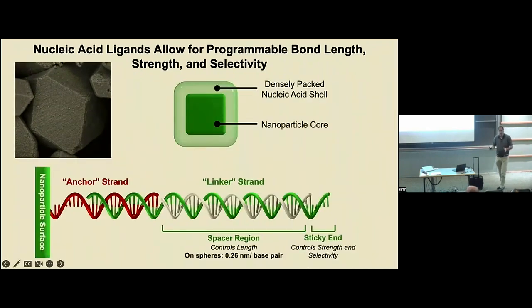Well, we were getting stuck in kinetic traps, right? We were using longer oligonucleotide lengths, and the bonds were actually too strong. And so we were stopping en route to crystallization. And so the trick was to build architectures that maintain directionality. Just tagging things with DNA doesn't work here. Density is really important. Having oligonucleotides all the way around the structure, forcing the oligonucleotides to stand upright and adopt the directionality imposed by the rigid particle core is actually quite critical in building these types of programmable atom equivalents.